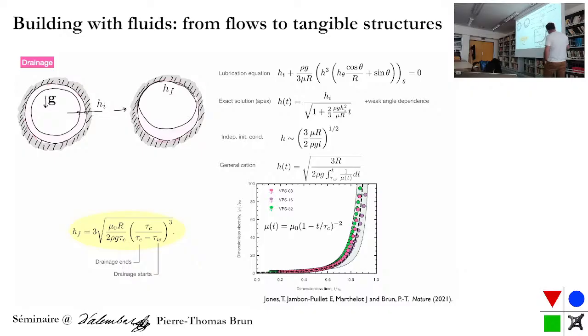So this suggests that if I want to change the thickness, I have to change the polymer that I'm using. But this is forgetting that actually you can truncate this curve by mixing things and not injecting right away, right? And this is what we call the working time or procrastination time, right? So you mix, you wait, and then you push the bubble. And so that means that basically you can make your curing time appear shorter, so tau c minus tau w, and so you can make your thickness become larger. You cannot go the other way around.